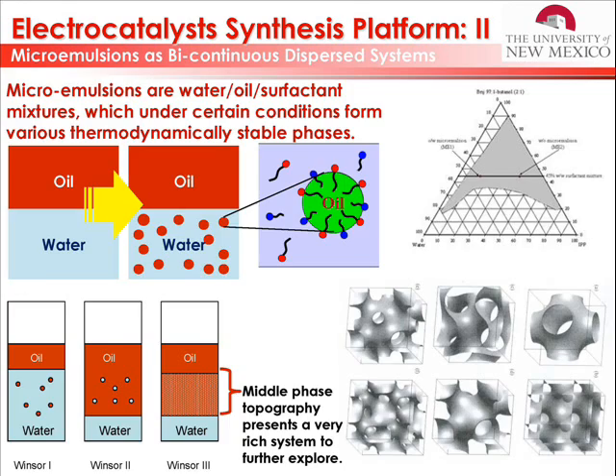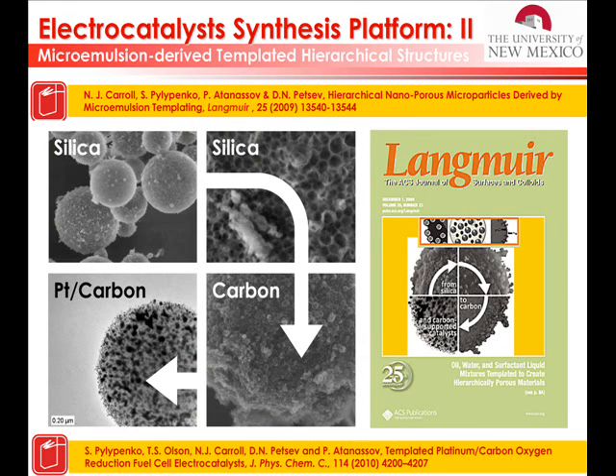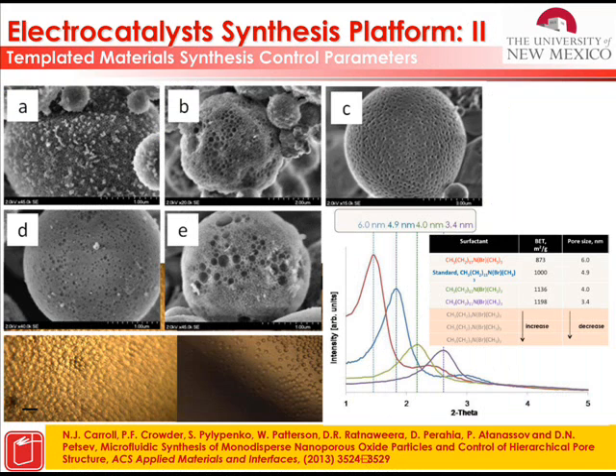So what is now left is essentially to make a template of it. What we did in our laboratory is we make silica inside the water phase of the microemulsion droplets, and then we wash away the oil, and then we impregnate with a carbon precursor, and then we take away the silica by etching, and you end up with a three-dimensional structure which is hierarchical. It is hierarchical because you have a template of very small particles, very small pores that are not from the microemulsion, but these small pores are from the micelles that are in excess. So you have micelle templating, microemulsion templating, and the entire particle templating. You have 3 levels of control if you need.